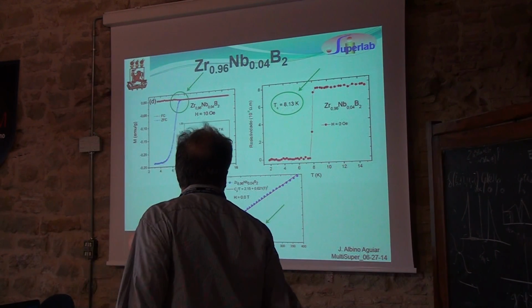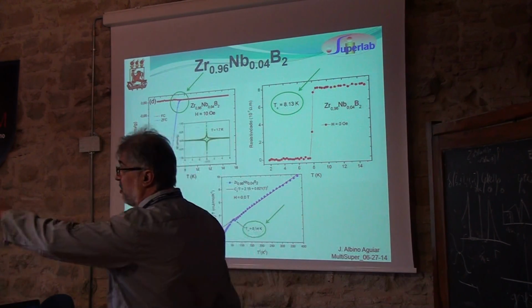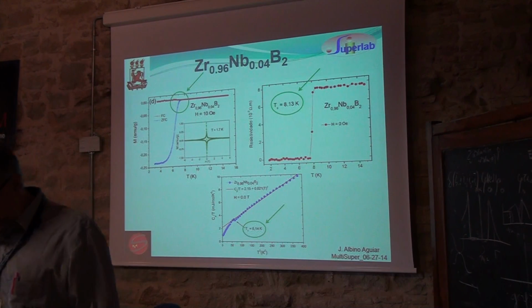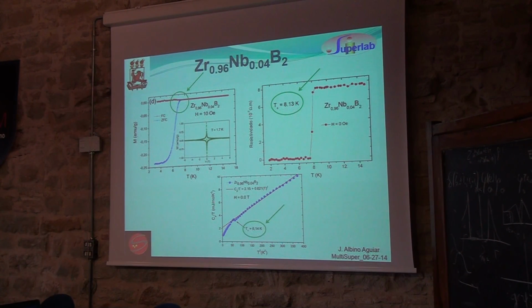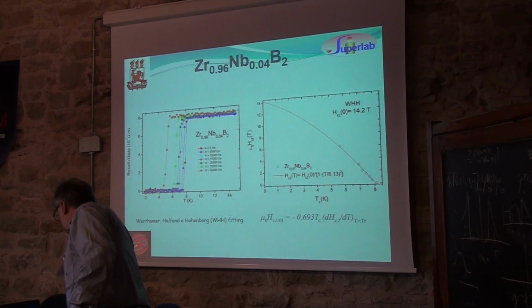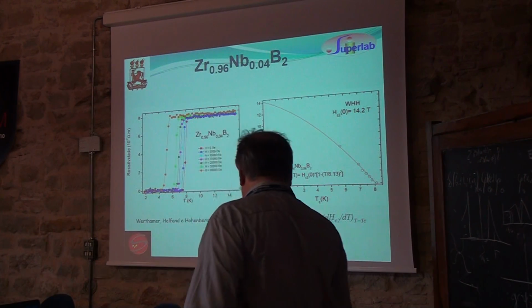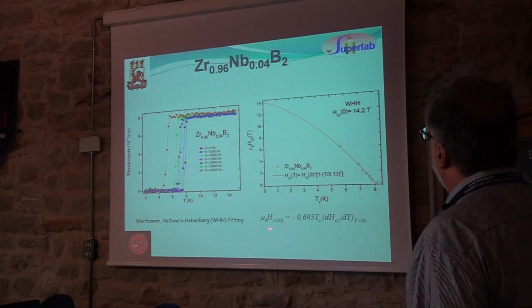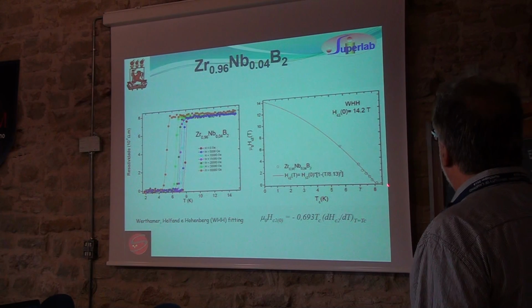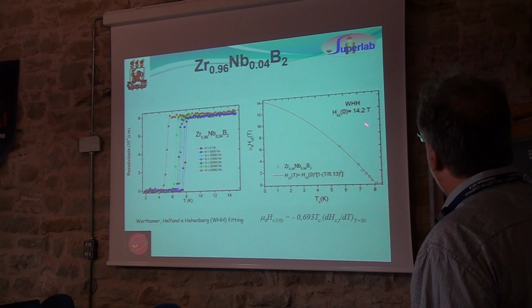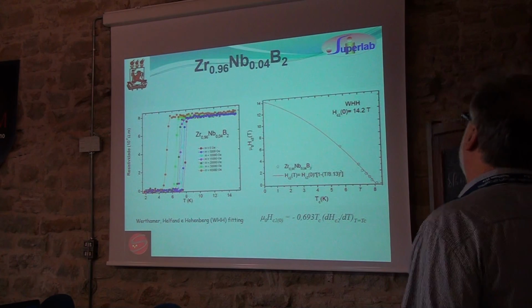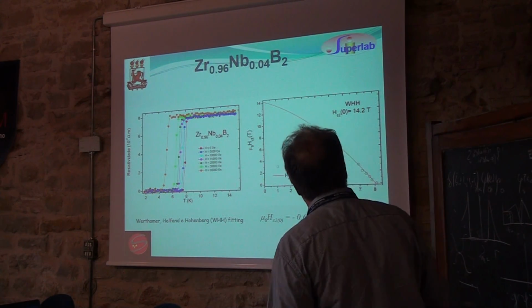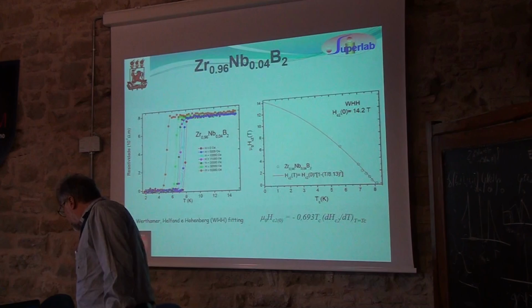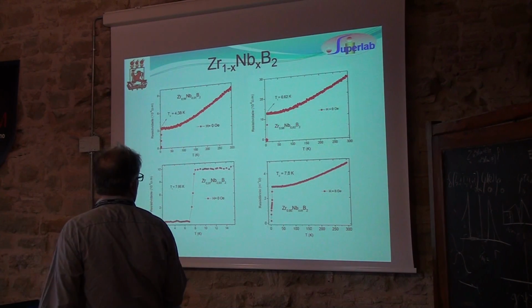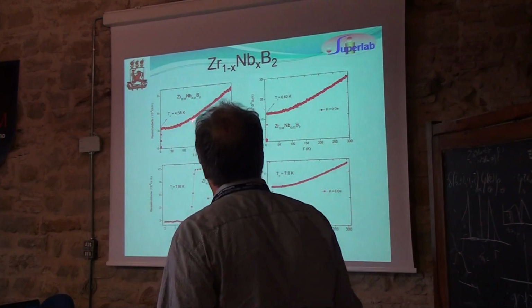The coherence length for both samples is of the order of 4 nanometers, 4.5. You can take it from the second critical field. Again, here the data to get the HC2, you can fit, and then you get, it's high. It should be here, not here. So, I want to have more of the transition for all the samples.